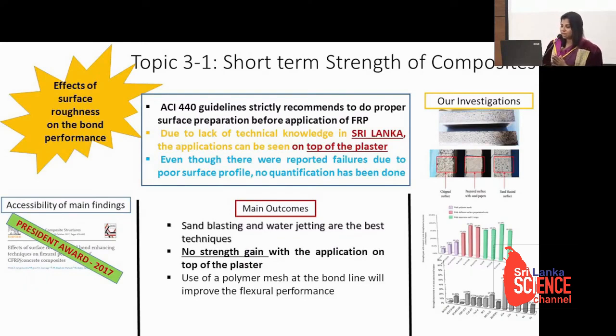So we conducted a series of testing to identify the strength gain with variation of surface texture, and found that the best suited techniques are sandblasting and water jetting. We didn't notice any strength gain if we apply this technology on top of the plaster, and also if we can place a polymer mesh, we can have enhanced flexural performance compared to all other systems.